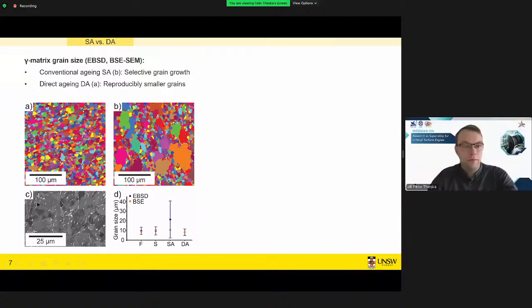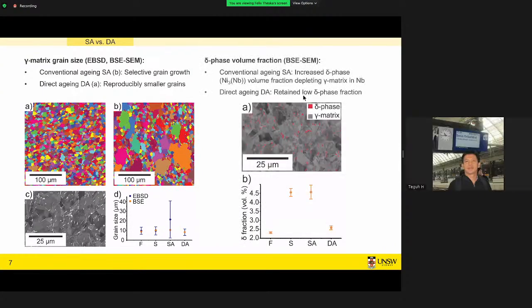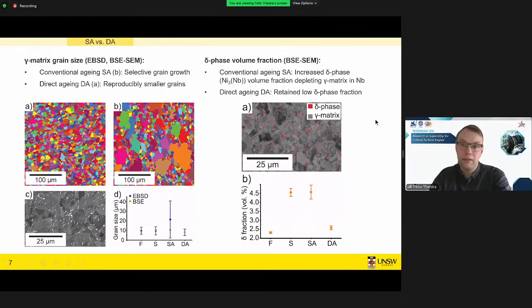In the bottom left micrograph, you see these white platelets in the gray gamma matrix. This is our delta phase, and because we have this really nice contrast here, we can start to quantify this as well. So here it's highlighted in red, and we can compare the delta phase volume fraction. And again, we see that the solution treatment does increase the delta phase volume fraction, whereas after the direct aging, the delta phase volume fraction remains lower.